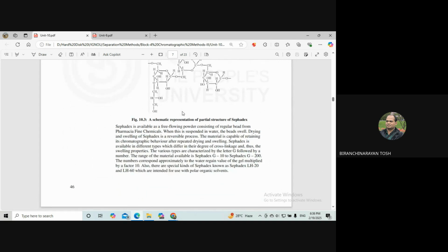So Sephadex is manufactured by a bead polymerization process. In this process, an alkaline solution of dextran of suitable molecular mass distribution is suspended in an organic solvent which is immiscible with water. Then stabilizers are added to stabilize the suspension. When the suspension is stirred to form an emulsion, epichlorohydrin reacts with the dextran matrix, forming glyceryl links between the chains. After the completion of the reaction, the product is washed thoroughly, allowed to shrink in a water-alcohol mixture, and then dried.